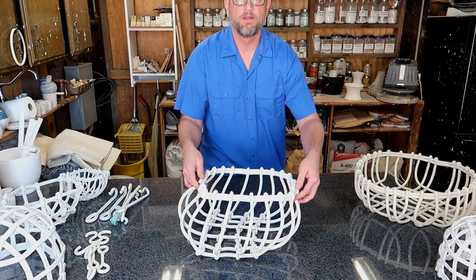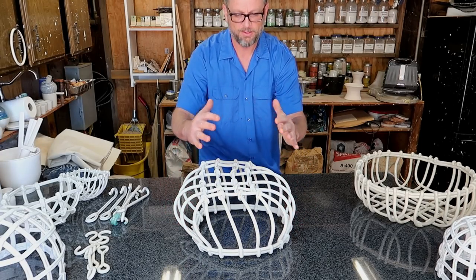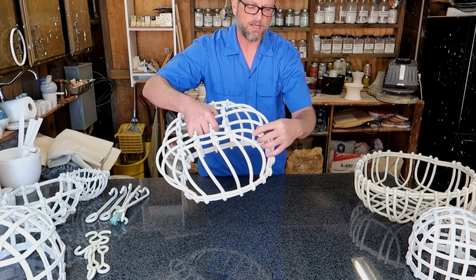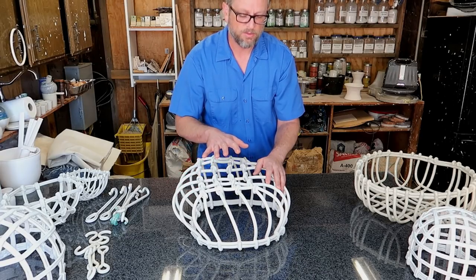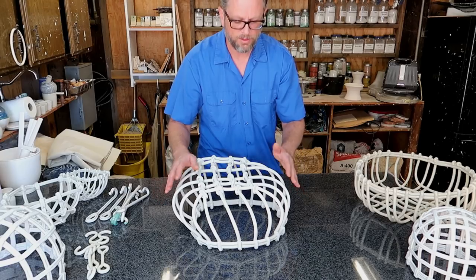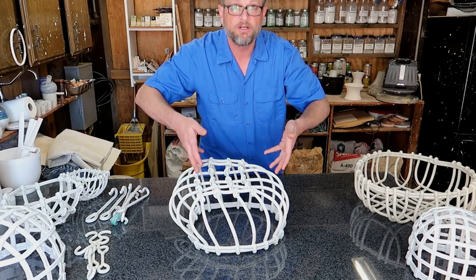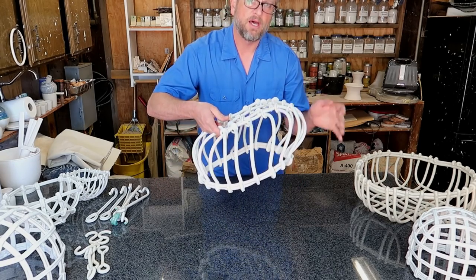Here's an example of a failure. Man, I was really bummed. This looked so good — nice and round, very similar in shape to something like this — it went well past the curve on the halfway point of the balloon. It made it through bisquing great, all the joints were tied. You can probably tell I could change my clay body to deal with some of this. I could also fire it a cone lower for glazing, as long as the glaze matures. I think some of this can be overcome with better construction. It's kind of like having a house with a bunch of two-by-fours going up and down and no sheeting, no angles — even the slightest breeze can knock it over. Although it was pretty, that is a real bummer — that was the top half of my kiln fire.